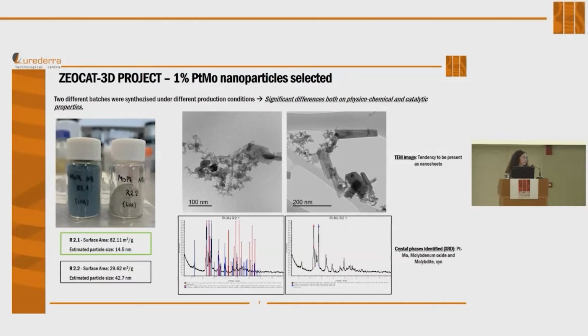Going more in depth in this composition, we carried out and produced different batches synthesized under different production conditions. As you can see, there are significant differences in both physicochemical and catalytic properties. Here in the image, you can see visually that the appearance was really different. Also, we got a higher surface area in one of these materials, which was the finally selected one, due to its activation in the catalytic behavior. So this material was more active than the other one.